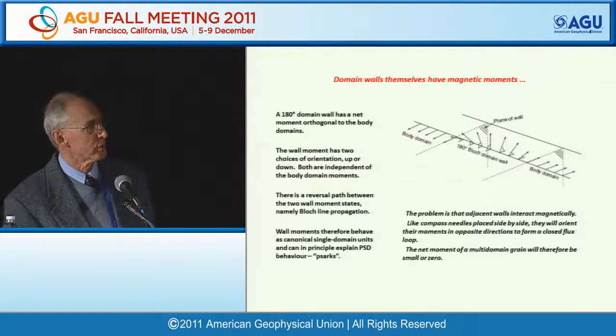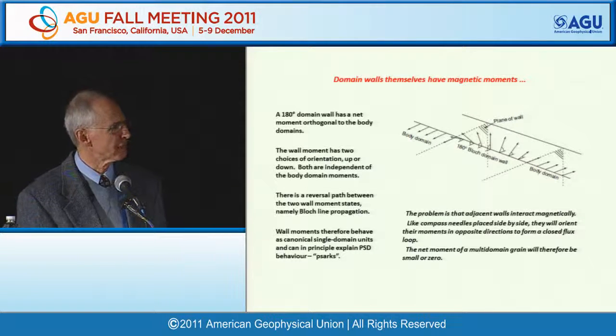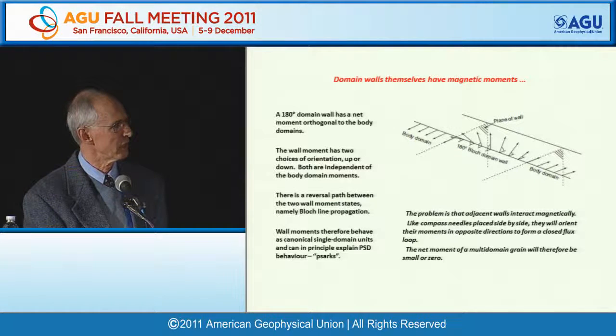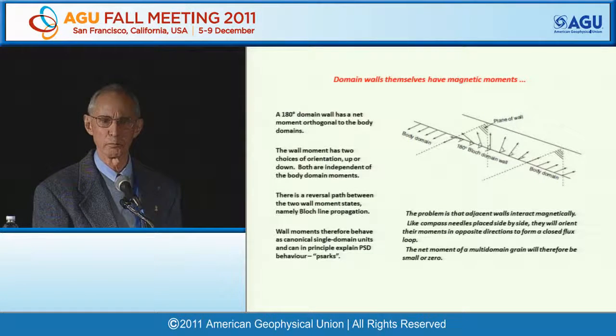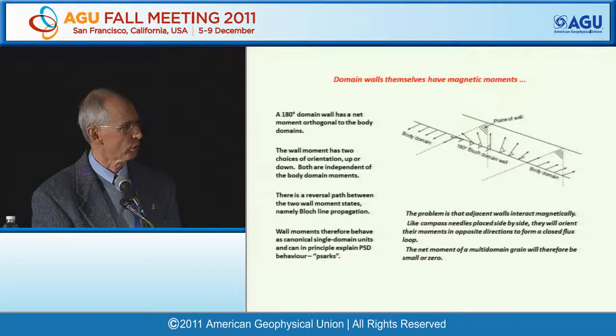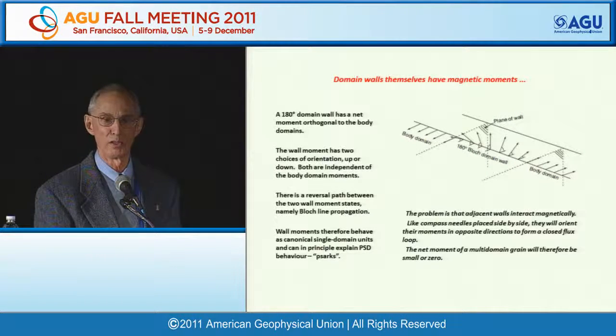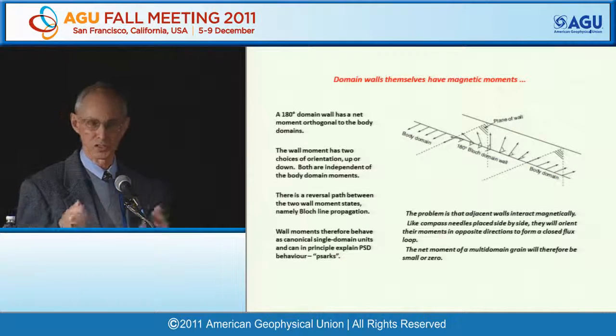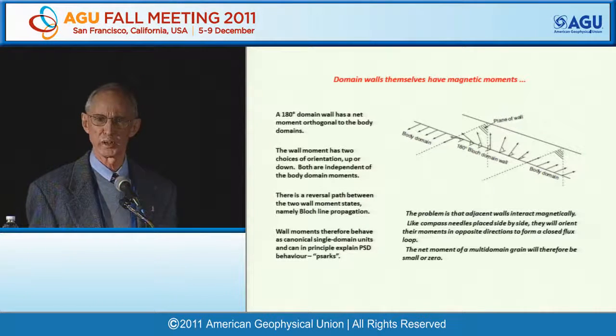An idea that I was very fond of in the early days turns on the fact that a 180-degree domain wall itself has a magnetic moment. The two body domains are horizontally magnetized here. The domain wall has a net moment which is up, or equally well could be down. There are two magnetic states, just as Néel prescribed for a single domain grain.